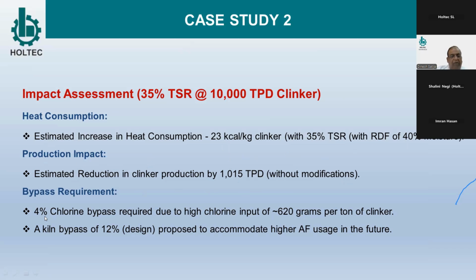The bypass requirement worked out now at 4% chloride bypass, because previously with 30%, 20%, there was no requirement. Now we required a 4% chlorine bypass. And we proposed a 12% design, because in case they go for a further increase in AF usage, it may also be used. So provision was kept for higher capacity.